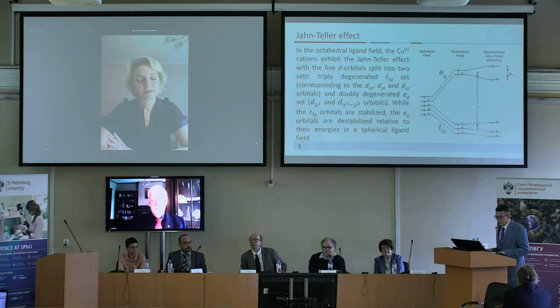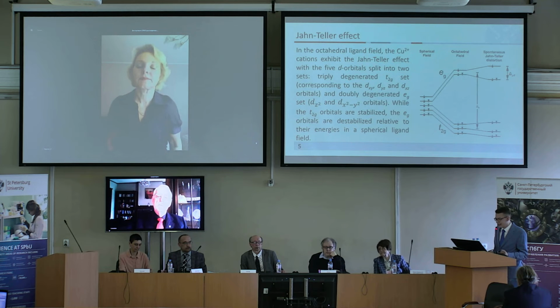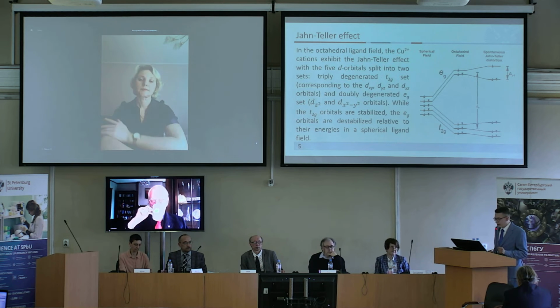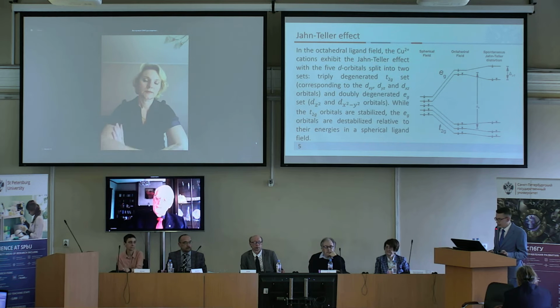The reason for such a wide coordination diversity is the Jahn-Teller effect. The divalent copper atom on the outer electron shell contains 9 electrons distributed over 2 sets of orbitals, t2g and eg, while the first set of orbitals is stabilized in the octahedral field, while the second set of orbitals is destabilized. The driving force behind the Jahn-Teller distortion is the unequal occupancy of the eg orbitals, which are separated because of the distortion.